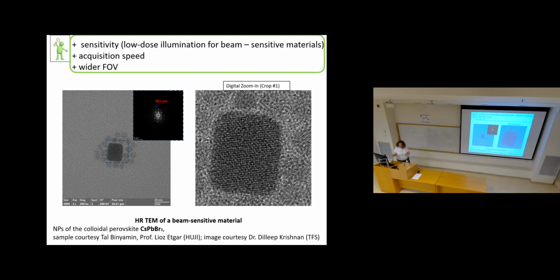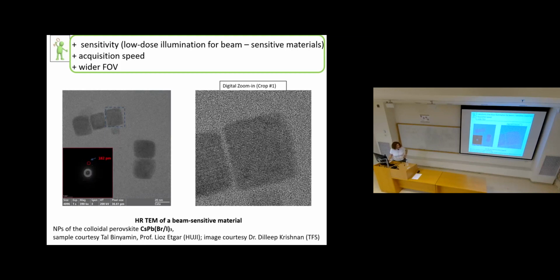Make the digital zoom. Enough pixels means we will get a full resolution image even if we acquire quite a large field of view. So this is another pair of images acquired of a similar sample, even less stable than the first one. You can see that it is not hard to get to the lattice image if the particle is properly oriented. And now, this is the image acquired with our CETA camera, with our microscope, on the standard gold palladium cross grating replica. 4K by 4K, 1 second.